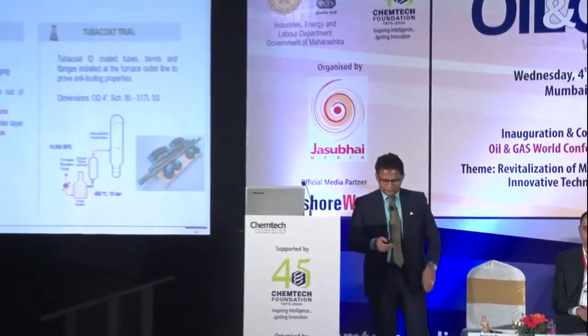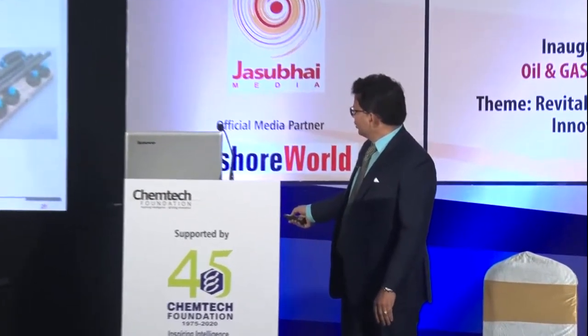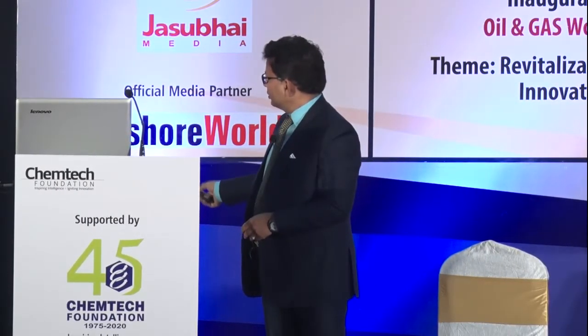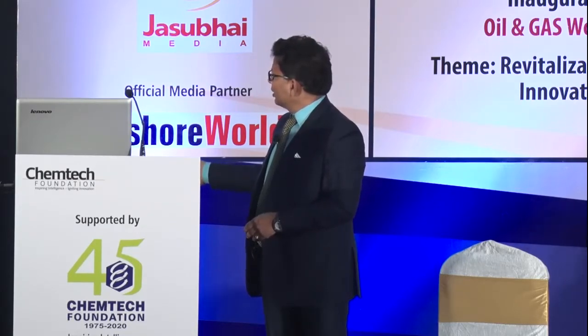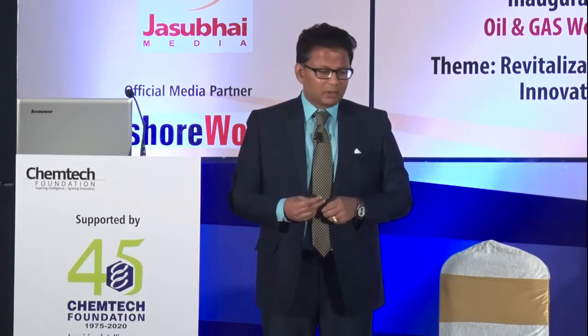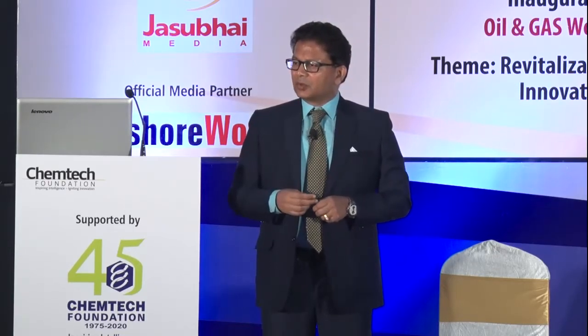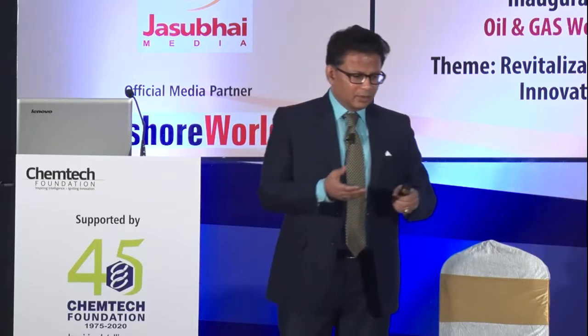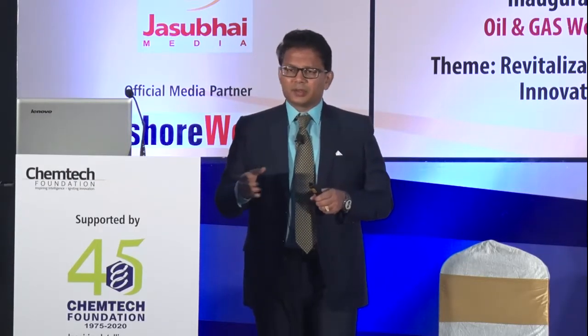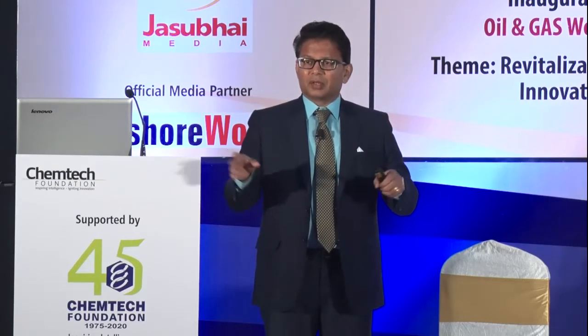Preheat exchanger upstream of the unit also gets the plugging, and the fuel consumption is very high because of poor heat transfer efficiency. So what you see in the picture is they installed the Tubacoat coated tubes along with the flanges and the bends, and the OD is 4 inch. And what you see as outcome is a very thin coke layer, there is a 75% reduction in the coke formation after 9 months. Coke is significantly easier to remove. You don't need a very high pressure, and online spalling frequency is now maybe 1/4 of the time you required it.